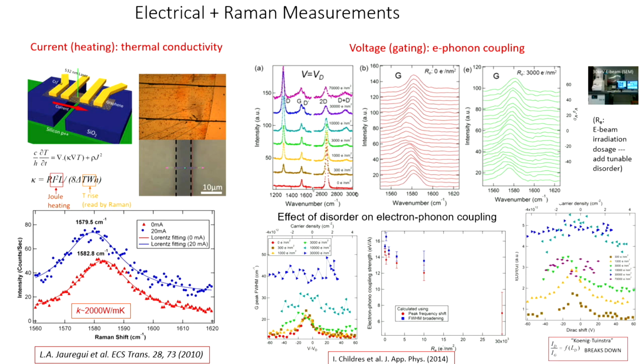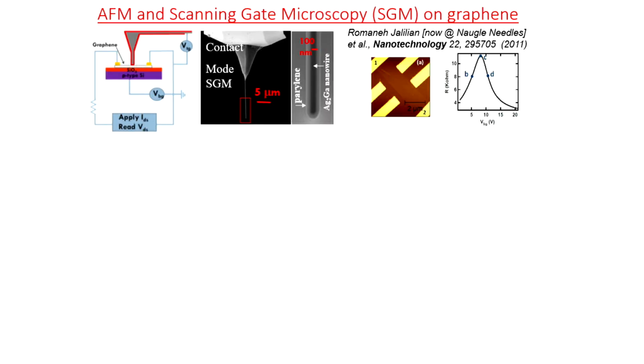That's an interesting way. And for Raman experts, this also allows you to question some of the usual convention in how people extract from the disorder-induced peak, say, relative to the graphene G-phonon. The ratio usually is treated as some kind of domain size, but this is actually clearly dependent on current density and gate voltage.